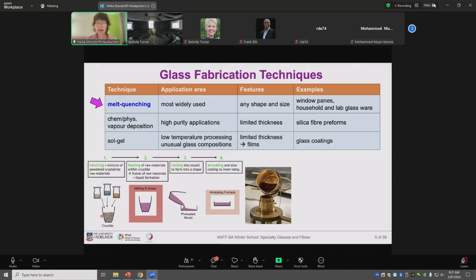If we make glasses in smaller quantities, like at Optofab Adelaide Hub, the crucible is placed in a furnace, heated up, and these raw materials, they first melt, the lower melting crystals they melt, and the higher melting crystals they dissolve in the glass melt. So that after a few hours a clear glass melt is obtained, the crucible is taken out of the furnace and the molten glass is cast into a preheated mold, preheated at the glass transition temperature.